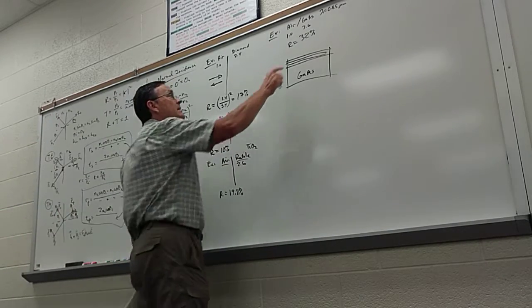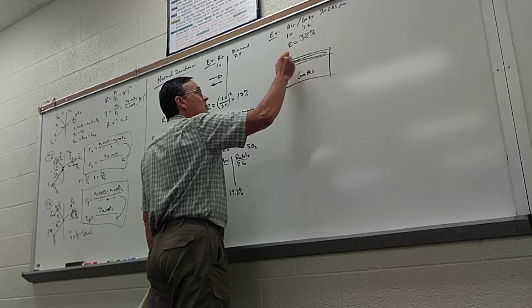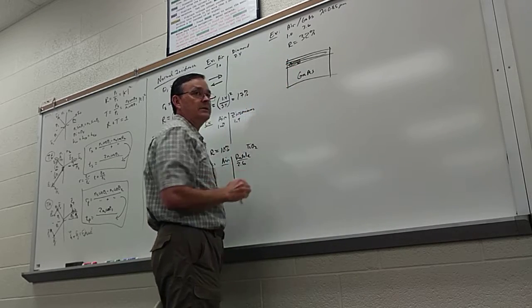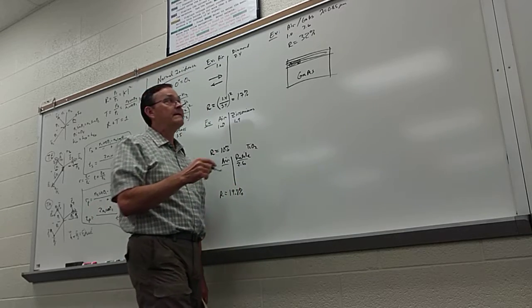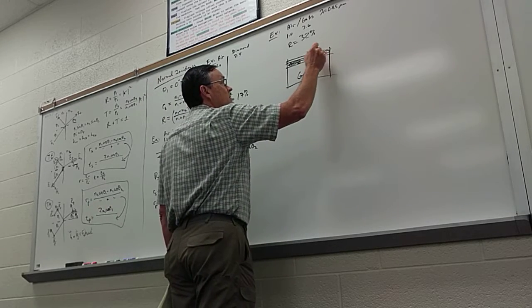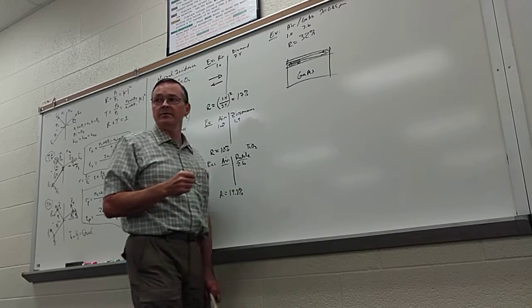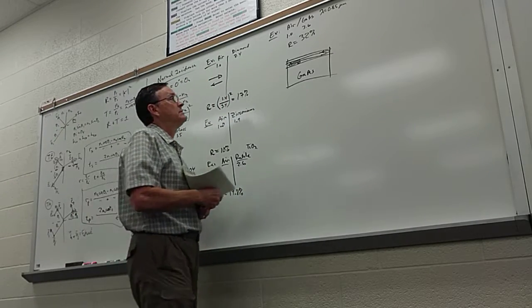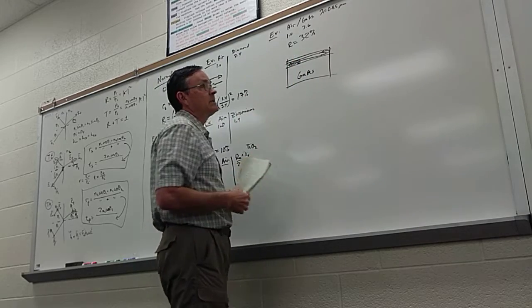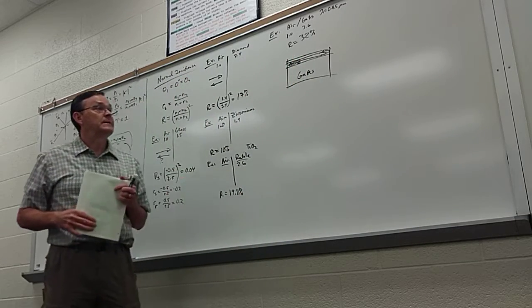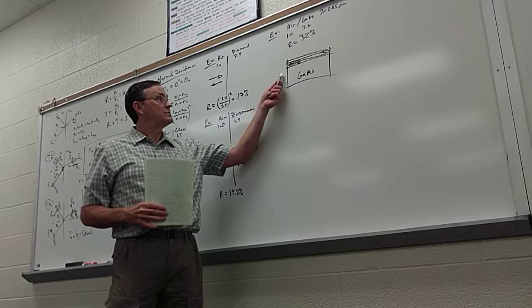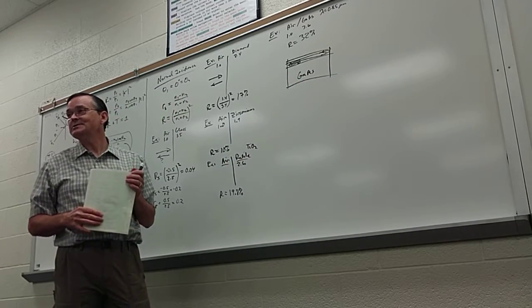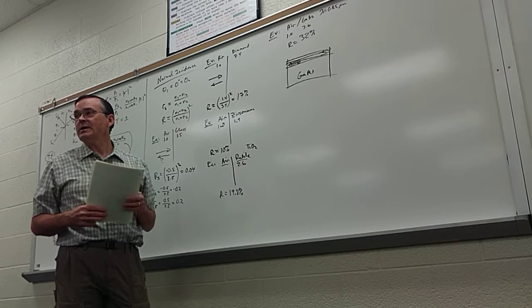And then this tells us that encountering that interface, we get 1/3 of the light reflected. And then over here, again, we get about 1/3 of the light reflected. And because we have so much gain here in the epitaxial layers when we pass a current through, even though we lose 2/3 of the light at each interface, we can still laser just fine because our gain is so high.